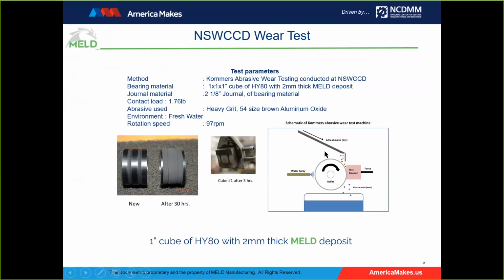But the whole purpose of coating is to get a lower rate of mass loss. That's the whole purpose of wear resistance. And so there's the standardized test. We took a 1-inch cube of HY80 steel. We melded a couple of millimeters of Inconel 625. This is the wear test, and the results were pretty impressive. We set a new value for rate of mass loss.